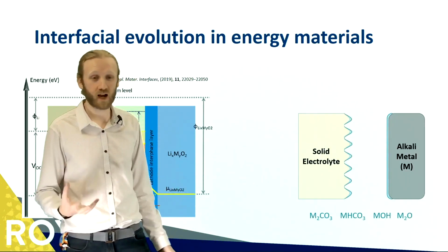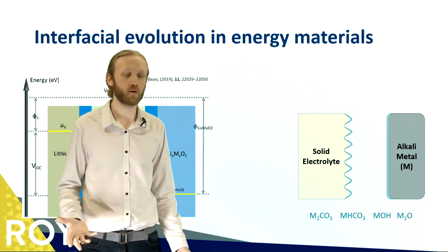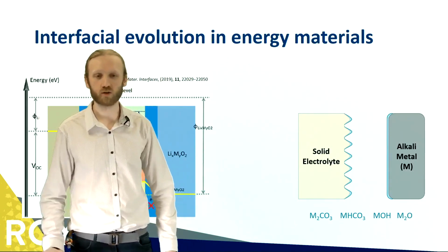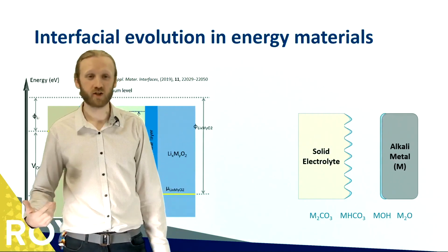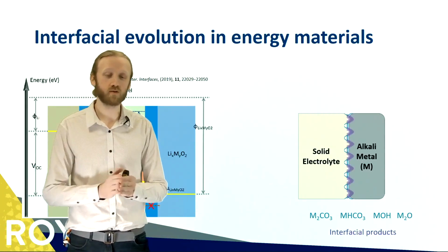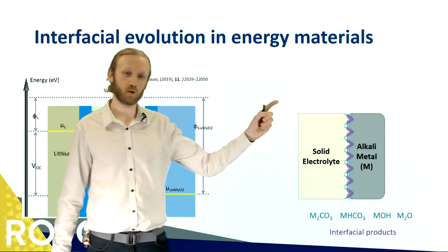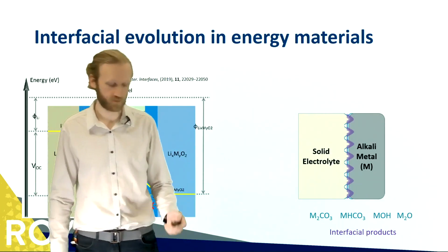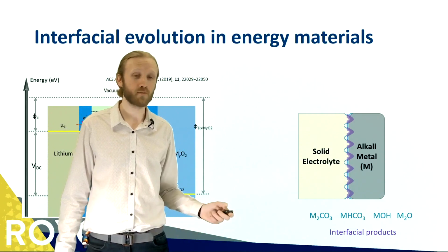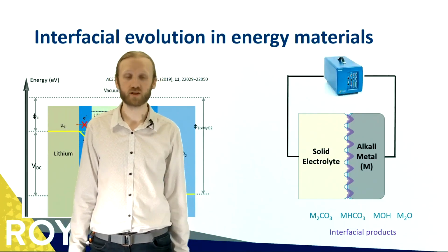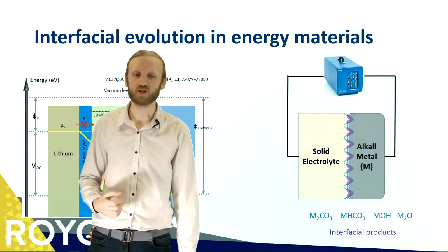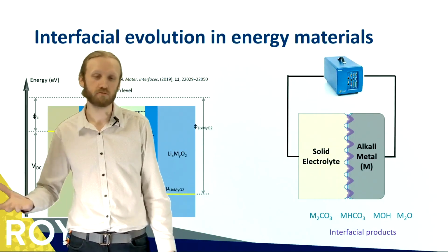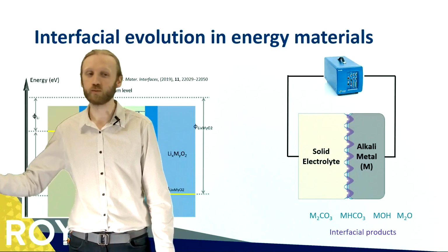The other thing is the inherent nature of lithium is it's very, very reactive. You tend to form these hydroxide and carbonate species on the surface. And as I mentioned, when you bring these two things together, you don't get an intimate contact across the whole surface, but when you do get contact, you get some interfacial products. And these interfacial products may even evolve with cycling as we charge and discharge our battery over many, many cycles, which is why your phone battery doesn't have the same life it does now as when you bought it brand new.